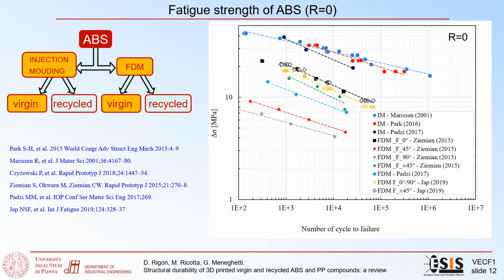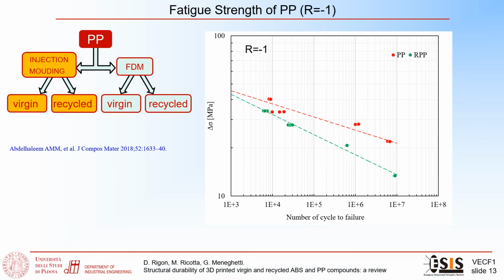Now, from different papers, we have the fatigue test results related to the virgin FDM ABS. As you can see, the best performance in terms of fatigue strength is obtained for a 0-degree orientation, and the lowest was obtained for a 90-degree orientation. Regarding the polypropylene, just the comparison between the virgin and the recycled injection molding material can be done, and here we see the difference in terms of fatigue strength with respect to the virgin and recycled polypropylene.